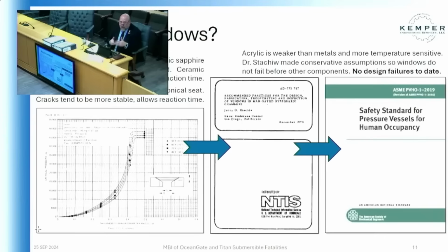So when it comes up that it was a very, very conservative curve, yes, it was. He understood there was a lot of uncertainty. He understood that we could not, at that time, reliably compute a model to predict it the way we could with steel. So facing that uncertainty, he tested the failure a bunch, figured out a failure band, wasn't a solid line, a band of failures, and then put the design line well away from that.